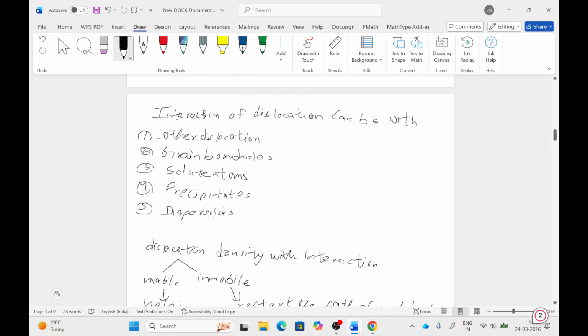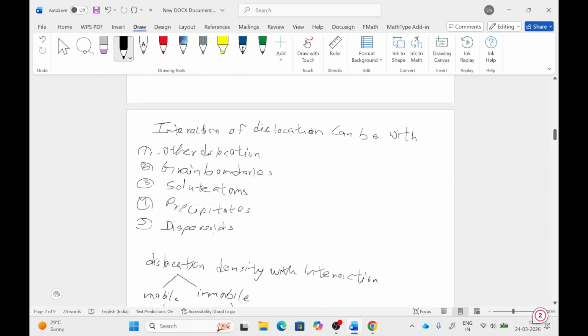So depending on these five features, there are five types of strengthening mechanisms. When the dislocation interacts with other dislocations, that results in strain or work hardening. With grain boundaries, it is grain boundary strengthening. Grain boundaries also restrict the path of dislocation.